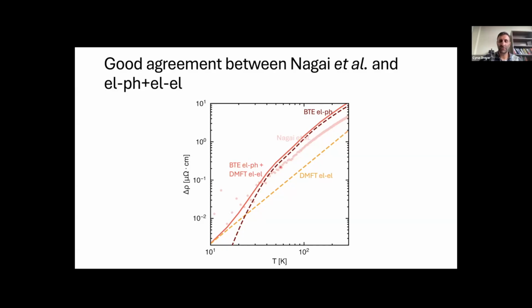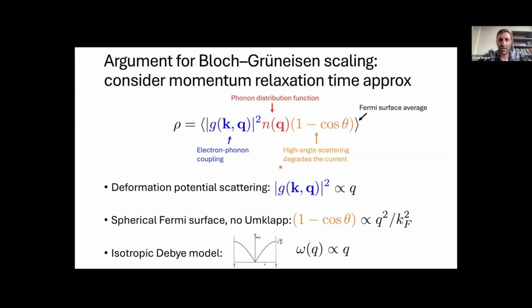So why in electron-phonon do we have a T-squared regime? To understand it, we first have to go back to why we expect this T to the fifth regime at low temperature. The reason can be understood if we consider the momentum relaxation time approximation of the resistivity, which includes an electron-phonon coupling matrix element, a phonon distribution function, and a term that selects out the high-angle scattering that actually degrades the resistivity.